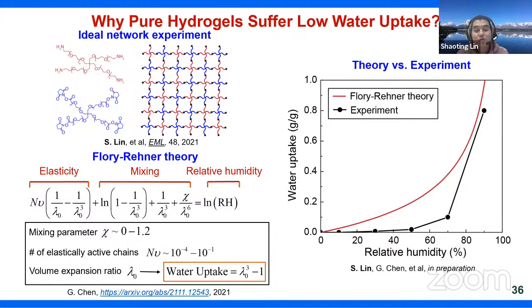And given this understanding and the preliminary study, eventually we can really well control. For example, the first step is really to eliminate the defects in the system, and the next step is to readily control these defects in the system. So for me, I demonstrated capability for controlling the entangled chain defects in the system, basically by controlling the hydrolysis of the amide group. Yeah.